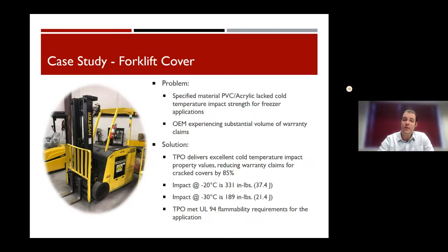So what we did was we were able to work with PMC and, using the same molds that they already had, transfer this over to a TPO material that, as Sam explained before, has excellent cold weather properties. And it was able to reduce all the warranty claims that they were receiving from cracking on this particular part due to the cold weather environments by around 80 to 85%. They reduced those warranty claims, so they were very happy with this transition over to the TPO.